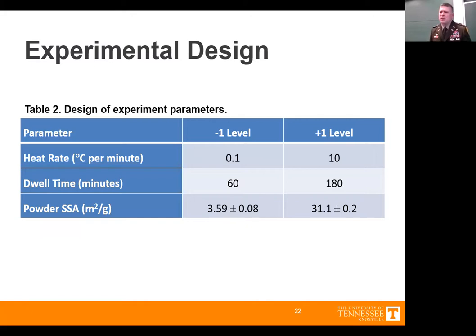So, the design of experiment: these are just the max and min parameters that I was using for all of my data. I used heat rates as low as 0.1 degrees C per minute, but again, I had a lot of problems anytime I got below 1 degree C per minute. So a lot of that data just had to be ignored because of the excessive grain growth.